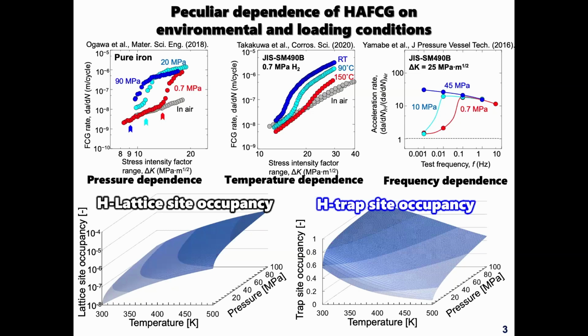When increasing the temperature, the hydrogen concentration at the lattice site, the lattice site occupancy, increases. But in contrast to this, the trap site occupancy decreases because the hydrogen atom is more activated at higher temperature, especially in the lower gas pressure range. So we thought the basic mechanism of hydrogen-assisted fatigue crack growth can be understood more comprehensively by focusing on the temperature dependence and loading frequency dependence from the viewpoint of the thermally activated process of hydrogen-dislocation interaction around the crack tip. This is the motivation of our studies.